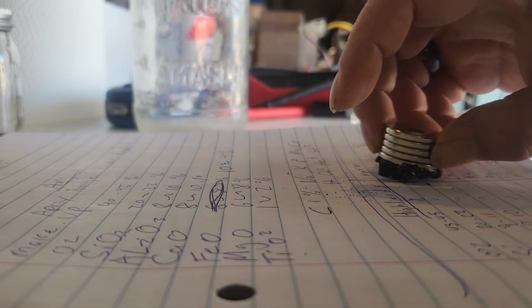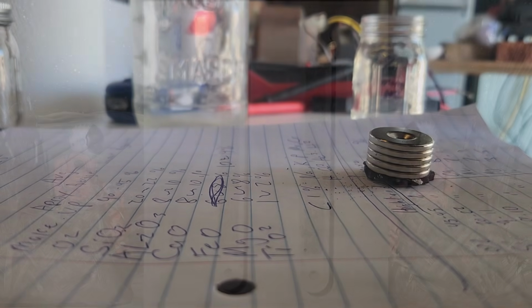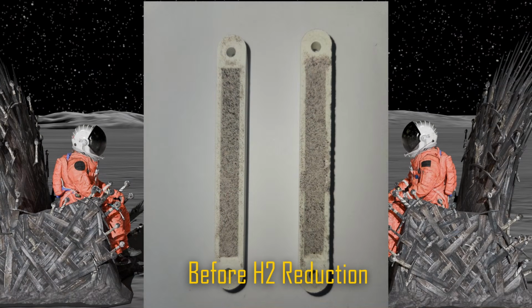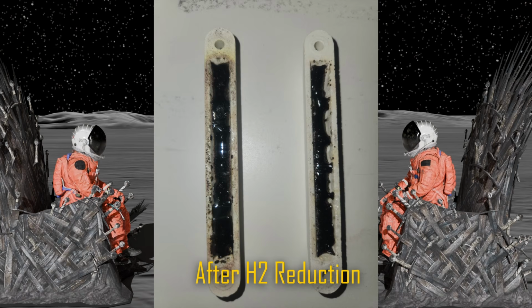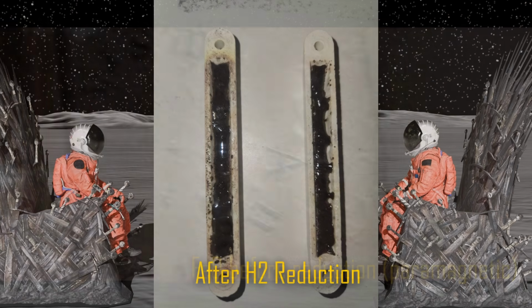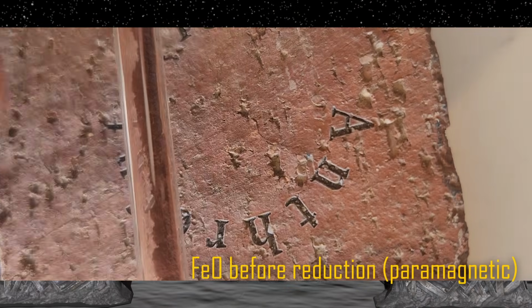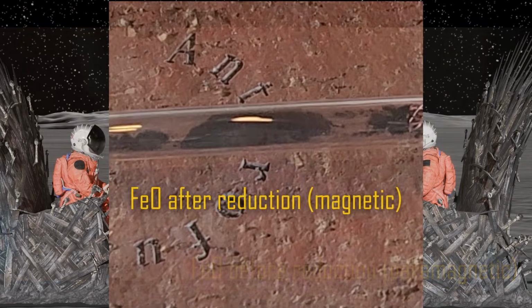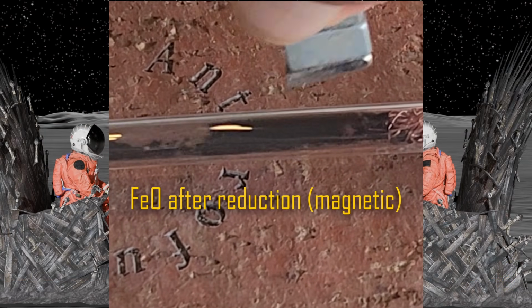You're getting any helium-3 that might be bound in the lunar regolith through a very simple process, as well as you're beneficiating the lunar regolith for your next processes, meaning that you've removed the iron, there's no more iron. It effectively reduces all the iron oxides into elemental iron. It also does this at a lower temperature, meaning the input energy for this process is a lot less. The byproduct from this process is H2O. Obviously, you're using hydrogen and it bonds to the oxygen, and that makes water.